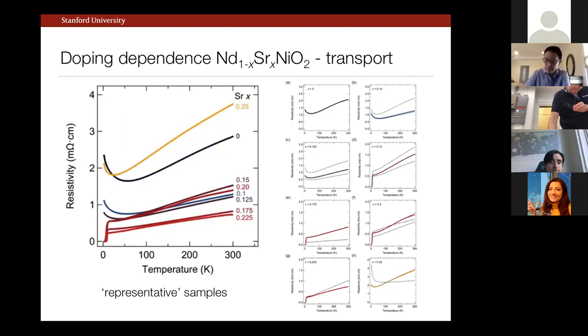Now, as I said, there is some variation sample to sample. So this kind of figure should be taken with some care, if you will. We've tried to show you representative variations here. These are nominally identical samples, different synthesis runs, but all other things being equal, what you can generally see is that in most cases the temperature dependence is qualitatively similar, but in detail there can be significant variations up to a factor of 2 in the magnitude of the resistivity and so forth.